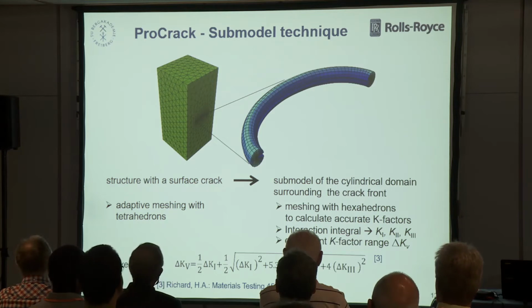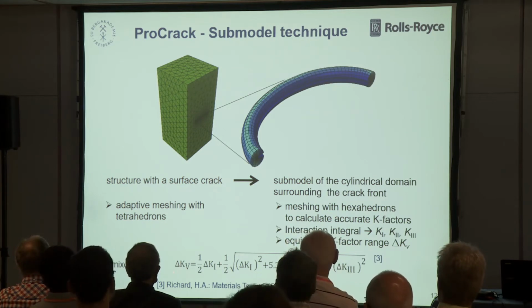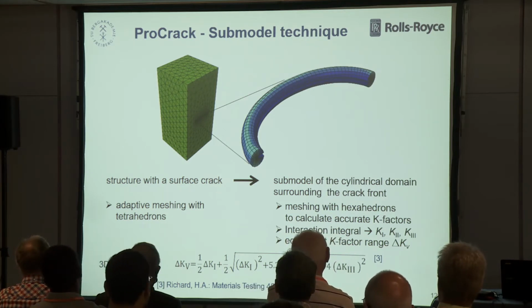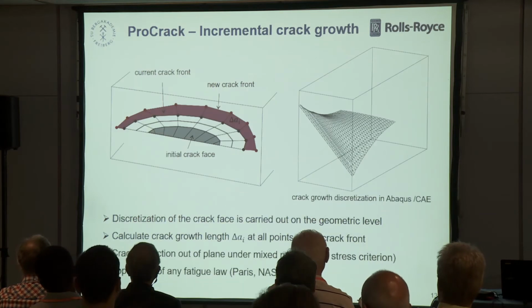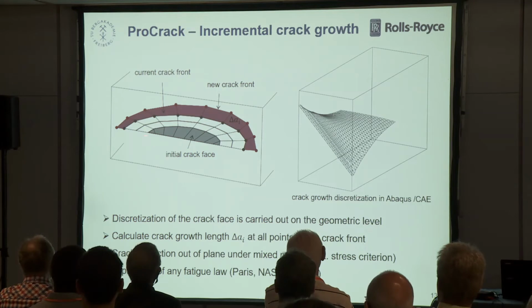Since we have mixed mode, we have to define an equivalent K-factor range for mixed mode, and here we adopt this method from Richard. We see our initial crack face, two steps of crack growth. We describe the crack growth by geometrical facets, not by the element mesh itself.